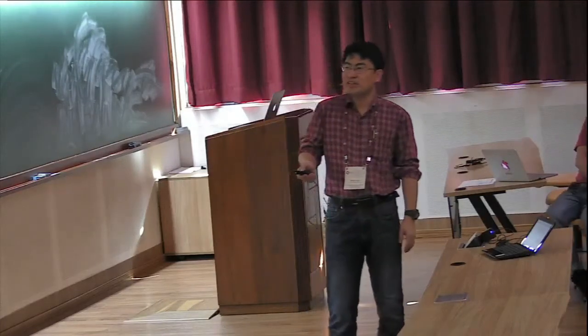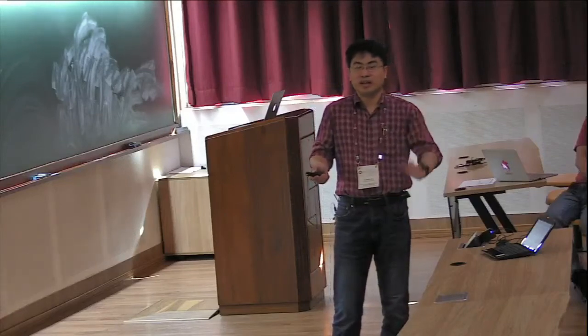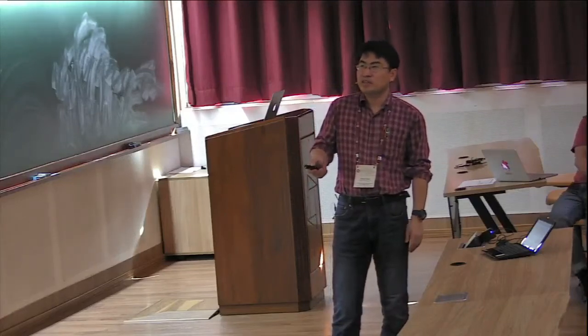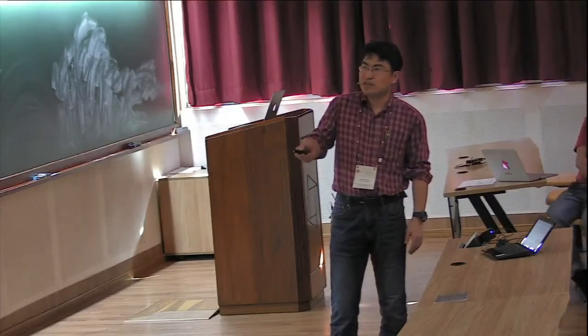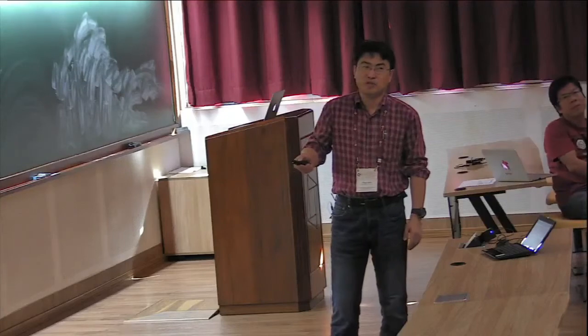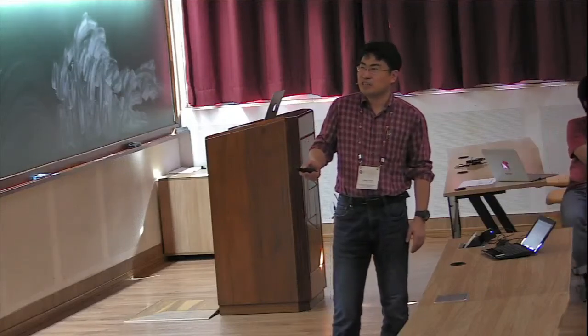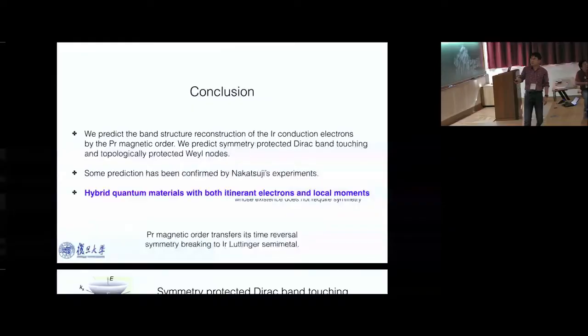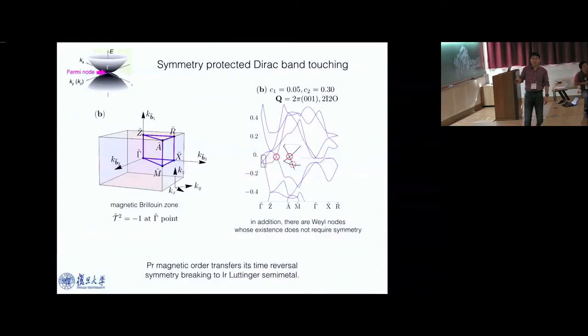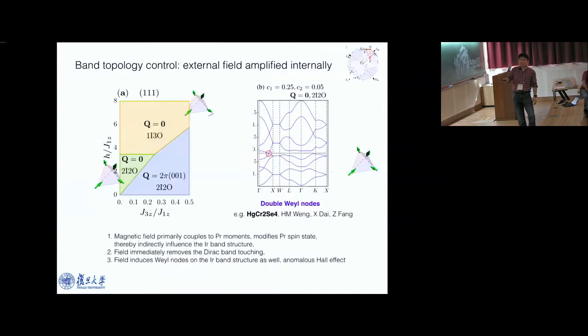Yeah, so this is the reason. If there is magnetism, before you turn on the magnetic field, in the presence of this particular magnetic order, this order has a particular symmetry, which gives you protection of the band touching over here. So this is protected by this magnetic translation. But if you apply a field, this symmetry is no longer there. So then you will not have this band touching here in the presence of the field. But you have band touching at some other non-generic points, non-highly symmetric points.